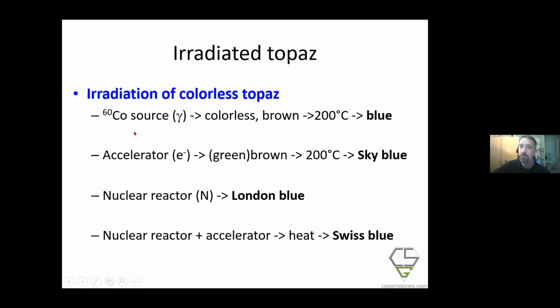So how can we design the color? Let's put it like this. In history, we have the first gamma sources which used cobalt 60 emitters. And with these cobalt 60 sources, you can take a colorless topaz, turn it brown, and after turning it brown, you heat it to a temperature of around 200 degrees and it turns blue. So while this brown color is not stable, it can be returned to the colorless or more or less colorless state if you put your topaz into the sunlight.